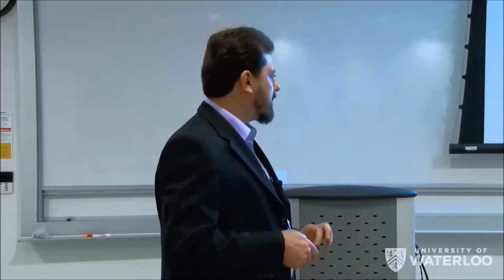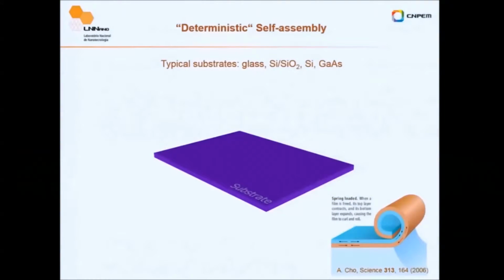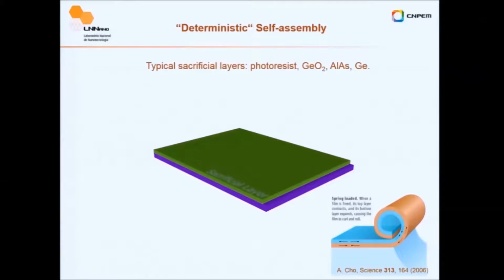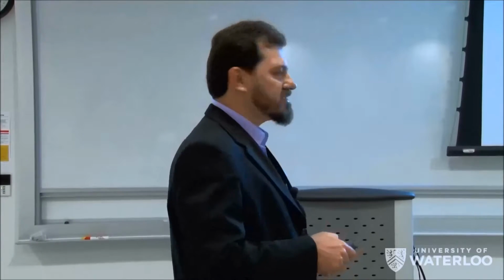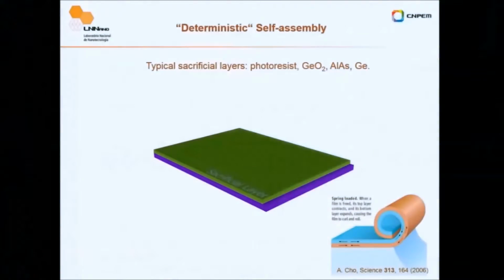In our case, the recipe is quite straightforward. We start with our basic substrate, which can be glass, silicon, silicon dioxide, gallium arsenide, and so on. Then you place a sacrificial layer, and there are plenty of solutions: it can be photoresist, or germanium dioxide that dissolves in water. Those who tried to make a MOSFET with germanium know this, and this is the reason why for years it never managed to work as a transistor. I actually use this knowledge, that it dissolves in water, as a sacrificial layer. So it can be aluminum arsenide in the case of semiconductors, or even germanium.